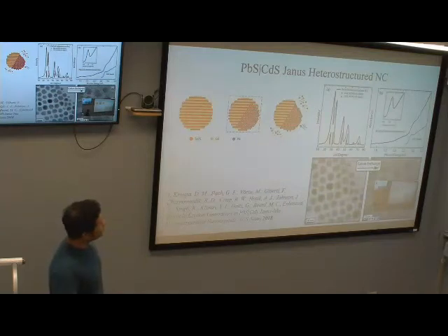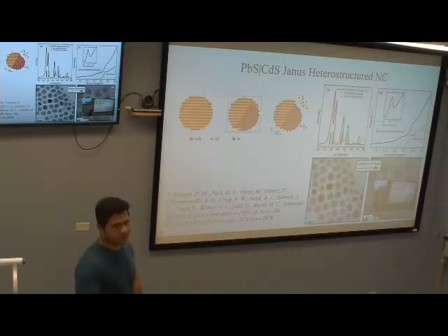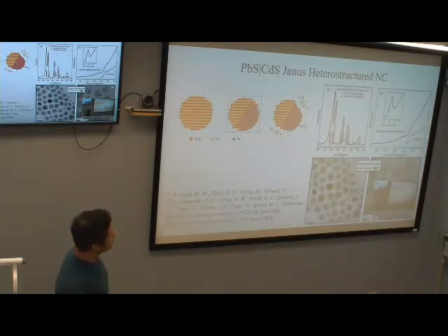This experimental result shows the absorption spectra before starting the cation exchange reaction, resembling pure cadmium sulfide. And after sitting in the lead solution, it started growing the lead part, giving a longer tail for the low energy part.